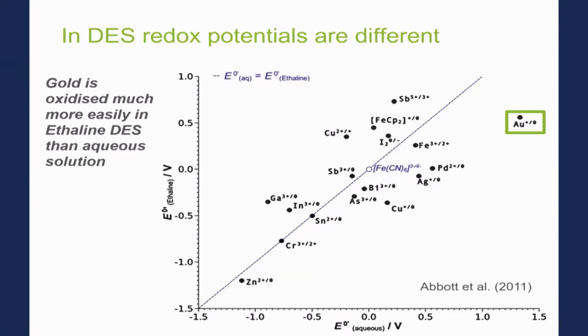Okay, now you say, why does gold dissolve? It's very hard to oxidize, but that's in an aqueous system. So here we've got the redox potential in aqueous systems for various couples compared to in our ionic liquid, and you can see that gold is over here. It has a much lower redox potential in our ionic liquid, so it's much more easy to oxidize. So anything below the one-to-one line here is actually easier to process and oxidize. Now this is just one ionic liquid. If you change the ionic liquid, you can change that pattern.